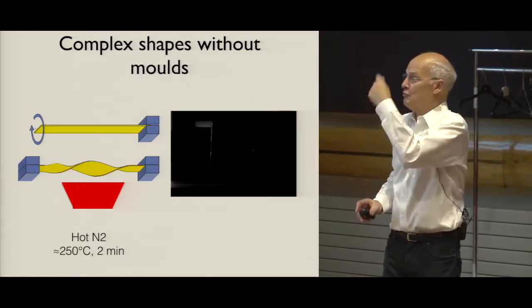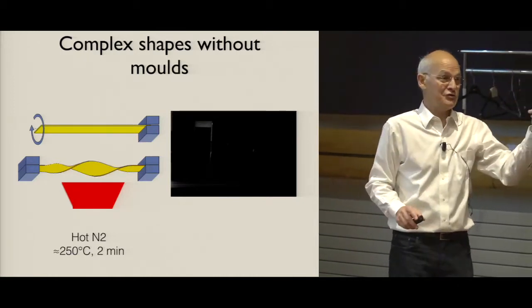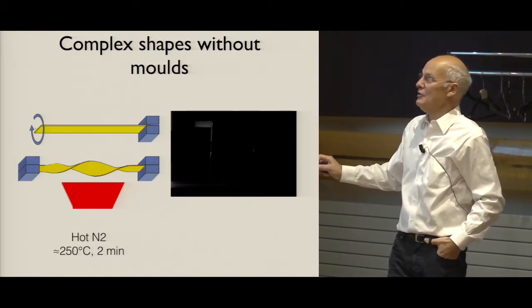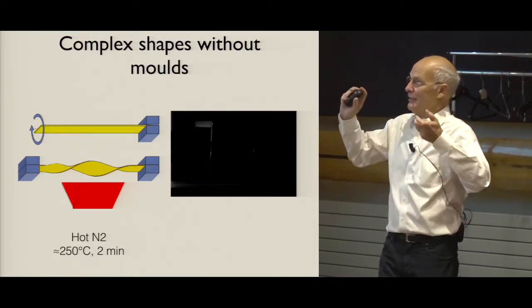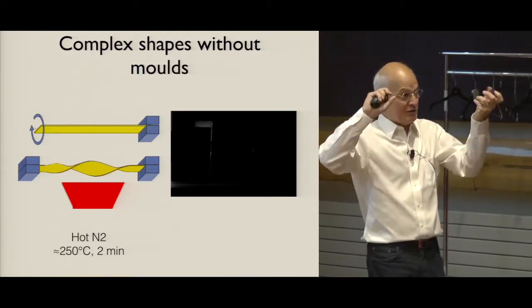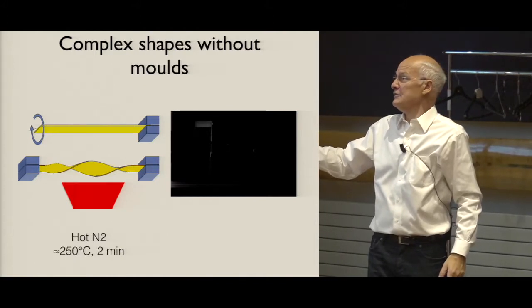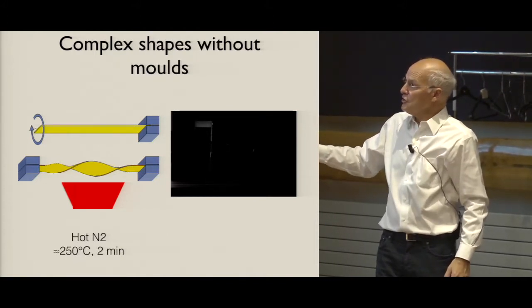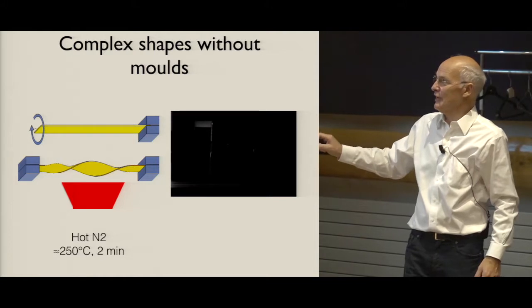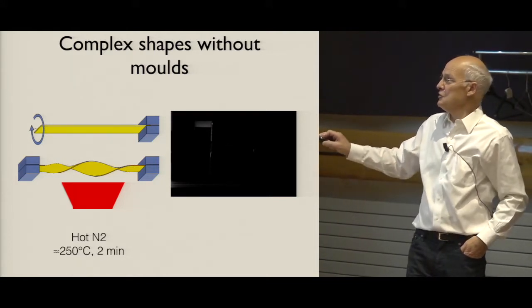So once we did it, and this is what we will play now, we can do the same things that glass workers do. So we took a rubbery vitrimer, a band. We deform it to a helical shape. So when you do this in a rubber, you build up the stresses, right? And normally the rubber will come back to its shape again. But if we heat it, not with a hair dryer, but under nitrogen so they don't oxidize, for 2 minutes, we will relax the stresses.